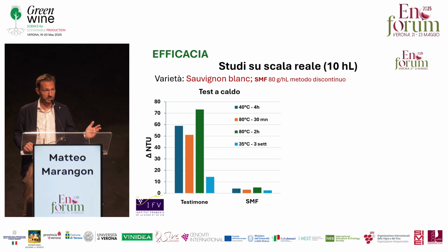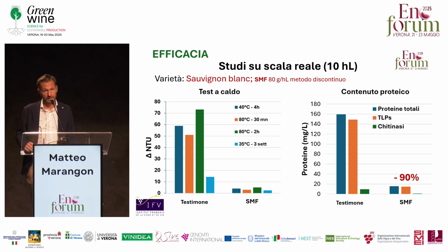We saw that the original sample, the control, I mean, was unstable. And you see these various thresholds exceeding, in any case, the 2 threshold. So cloudiness was invariably the result. With the treatment with SMF, even with the stringent test, we proved that instability was very limited. Basically, full stability was obtained.